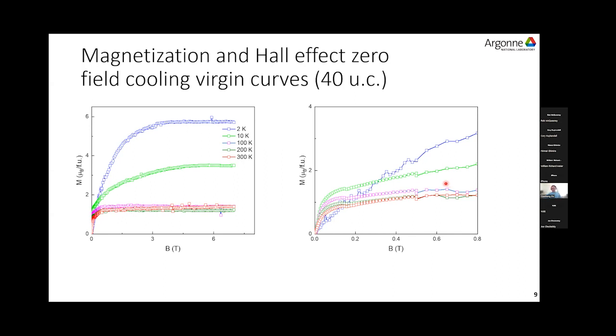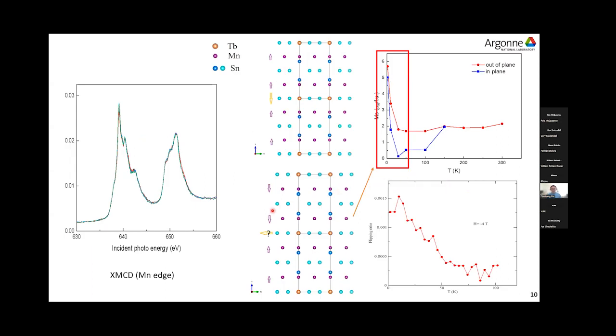Actually, this conclusion is confirmed by our XMCD measurements. For the XMCD measured at the manganese edge, there is no contrast for the low temperature zero field cooling XMCD. That means there could be no net magnetization at the manganese lattice. And then we could have one hypothesis: instead of a ferromagnetic order, the two manganese spin moments may align anti-parallel, and then there is no net magnetization in the manganese sublattice. Also, the terbium could become paramagnetic, which gives the rising tail in this saturated magnetization versus temperature curve. Actually, this is also confirmed by the flipping ratio in the terbium edge measurements.